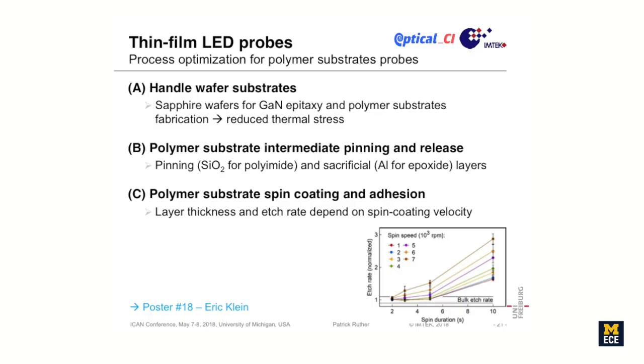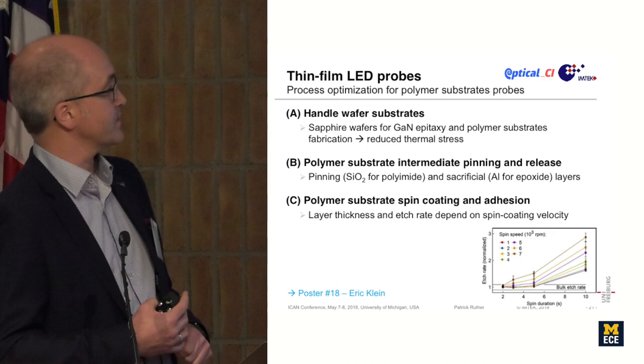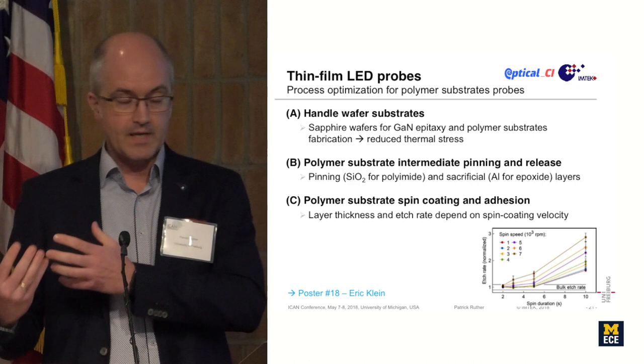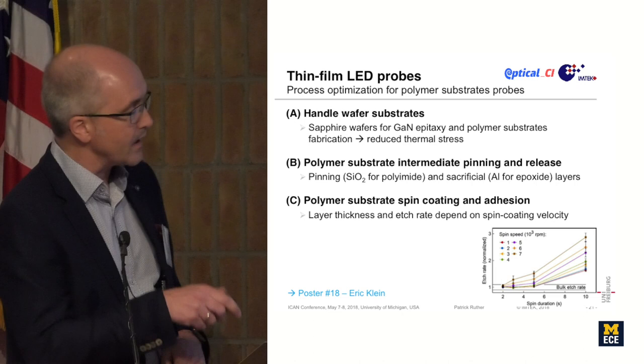Now the optimization that had to be done in particular for the purely epoxy probe included things like taking care of the handle wafers. You get the gallium nitride on sapphire, so we also use sapphire for the polymer substrates to minimize the mechanical stress, the thermomechanical stress, during bonding. We had to look at pinning structures so that we can fix the substrates on our wafer, but also we had to take care of how to release these devices.